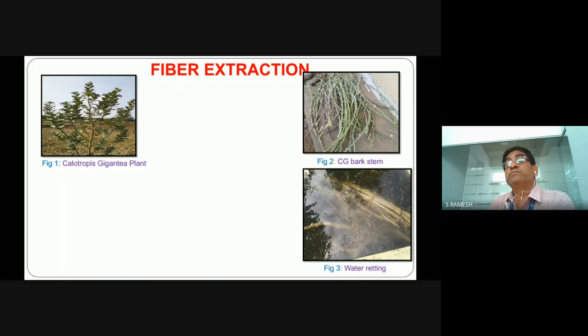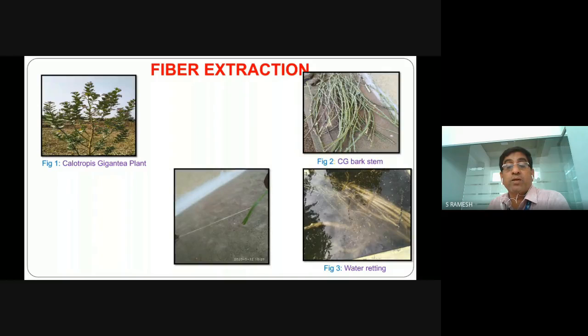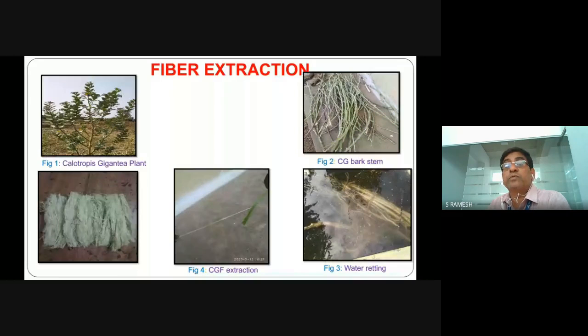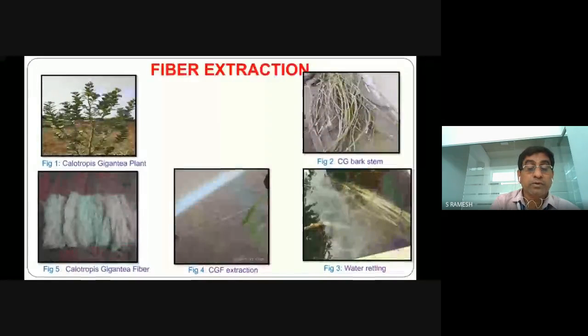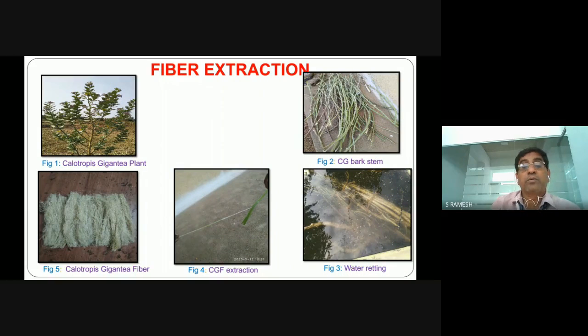Due to that, water penetrates by capillary action into the stem, and the fibers come slightly outside. Using a mechanical method, we extract the fiber after the water retting process. Finally, we get a cumulative of fibers, the Calotropis gigantea bark fiber. Generally, from a Calotropis gigantea plant, we can get two types of fiber: one from the fruit and another from the bark stem.